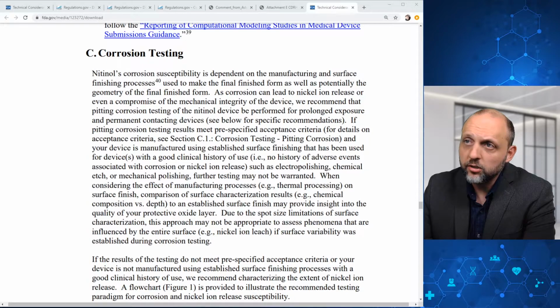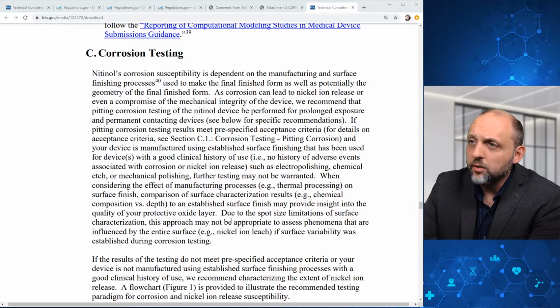If pitting corrosion testing results meet pre-specified acceptance criteria, and the device is manufactured using established surface finishing that has been used for devices with a good clinical history of use, such as electropolishing, chemical etch, or mechanical polishing, further testing may not be warranted. When considering the effect of manufacturing processes on surface finish, comparison of surface characterization results to an established surface finish may provide insight into the quality of your protective oxide layer. Due to the spot size limitations of surface characterization, this approach may not be appropriate to assess phenomena that are influenced by the entire surface if surface variability was established during corrosion testing.